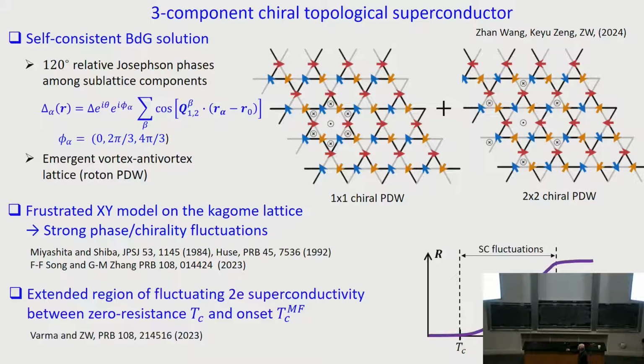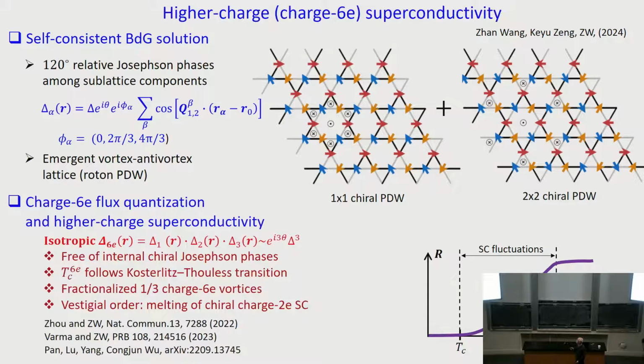So this is what we worked out, that if this is your mean field transition, then the phase fluctuation will drive the true superconducting transition to much lower temperature, exposing a huge region in which there is superconducting fluctuations. And it is in this fluctuation region that one might expect higher charge superconductivity. For example, I can now make a charge-6e object, which is the product of the 3 chiral components. 3 components, 0, 120, and 240. If you add the phases together, it cancels out. It's 0 mod 2 pi. So this 6e order parameter will not couple to the chiral phases. So as the chiral phases fluctuate strongly to kill the charge 2e superconductivity, this charge 6e will be a remaining vestigial ordered state, and that's the 6e state.